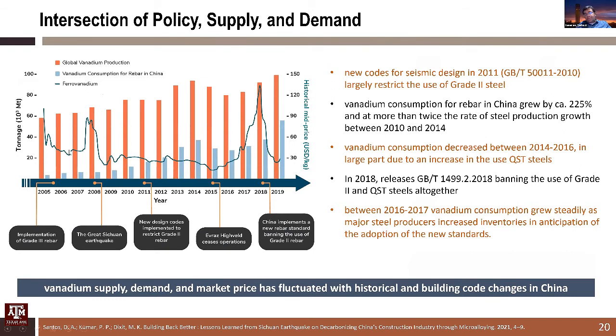This is a complicated graph, but I want to show a timeline of all of the events and all the different codes that have been implemented in China. You see the prices of vanadium here per kilogram, and that has fluctuated a lot because of these design codes coming in. And you can see that in blue is the vanadium consumption for rebar in China, really increasing massively from 2005 to 2019, from just a few thousand tons to almost about 60,000 tons. And the global vanadium production is shown in orange, and you can see how much the Chinese rebar production is increasingly capturing a large part of the market.